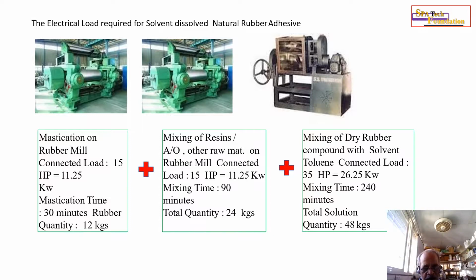You need a mixing mill, you need a sigma. Mastication on the rubber mill: connected load is 15 HP for a 12 by 30 size rubber mill, which is equal to 11.25 Kw. Mastication time is nearly 30 minutes. Quantity of rubber is 12 kg. It is mixed with resin, antioxidant, and other raw materials on the rubber mill. The connected load of the mill is 15 HP. The total time required is 90 minutes. Total quantity that can be produced is 24 kg.